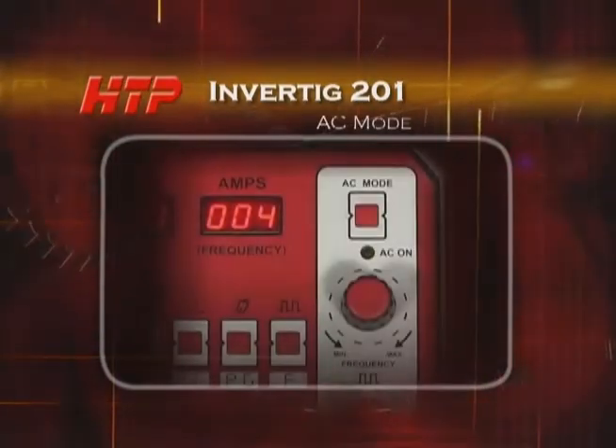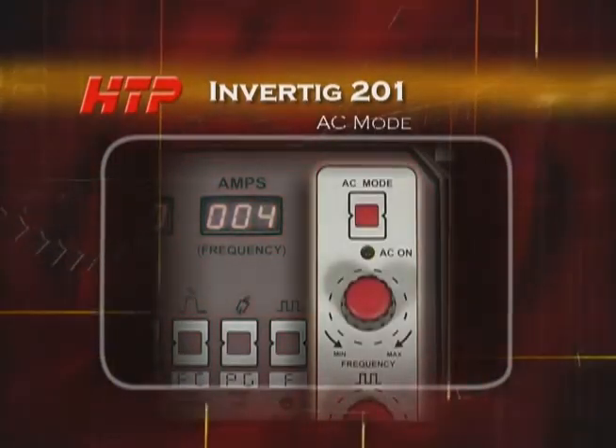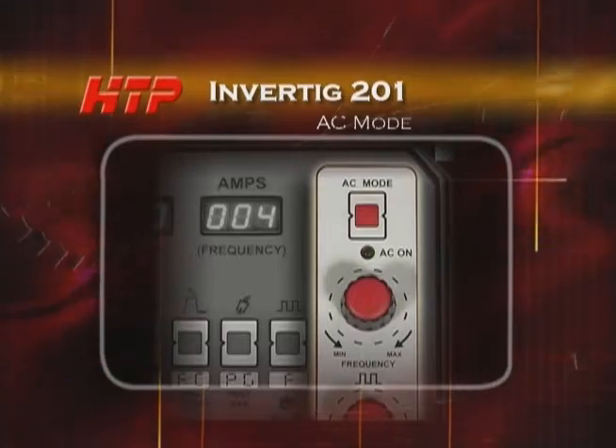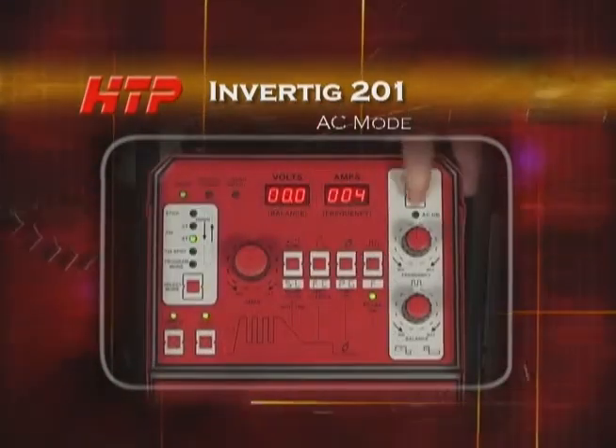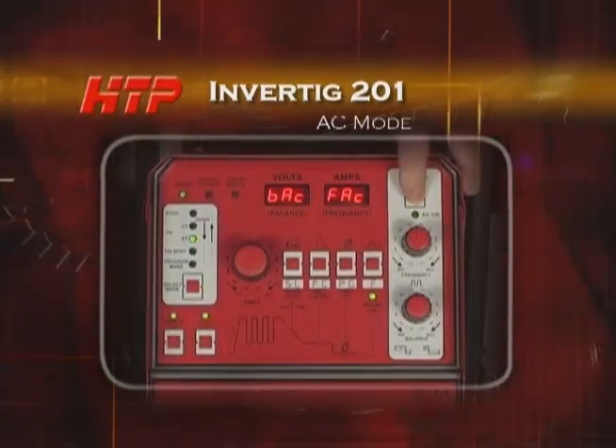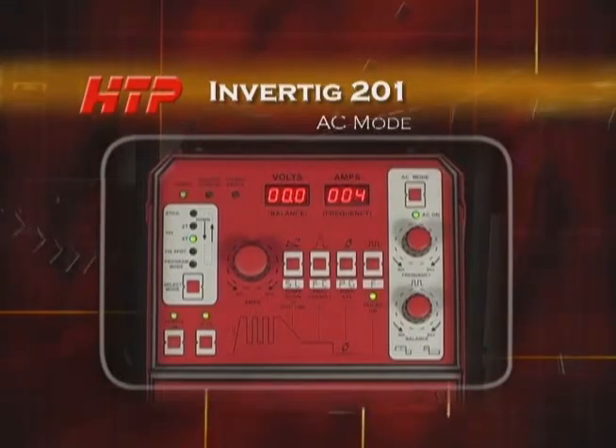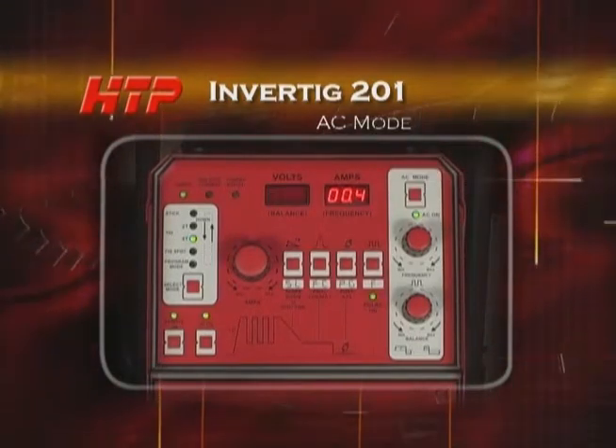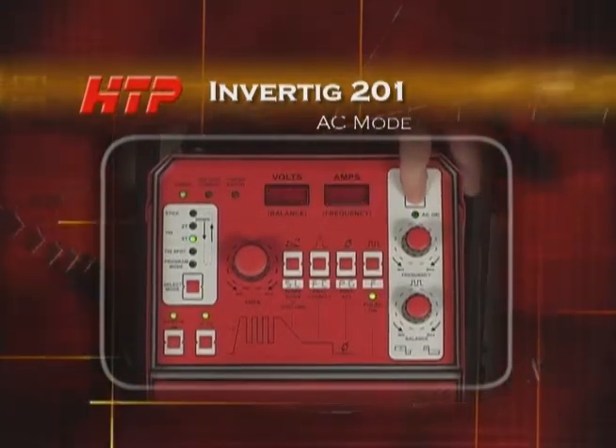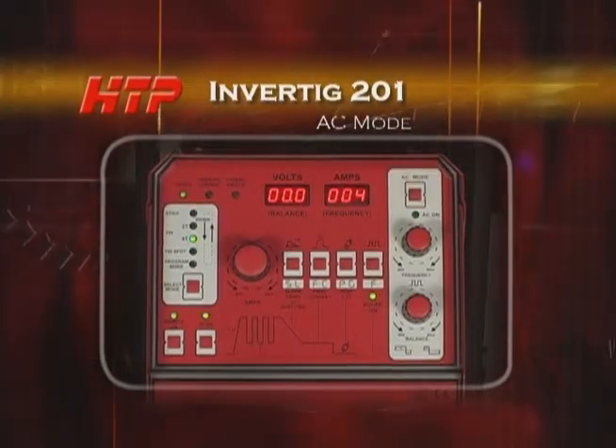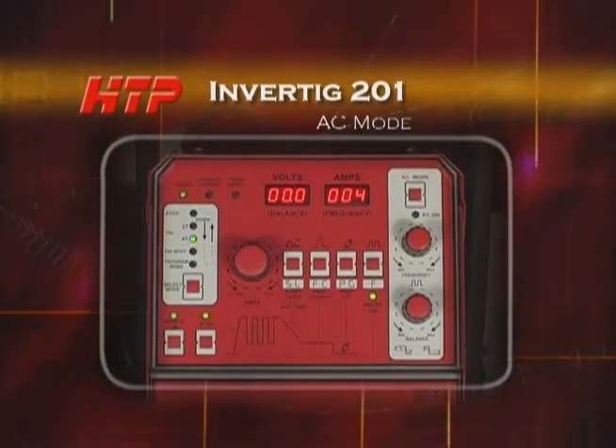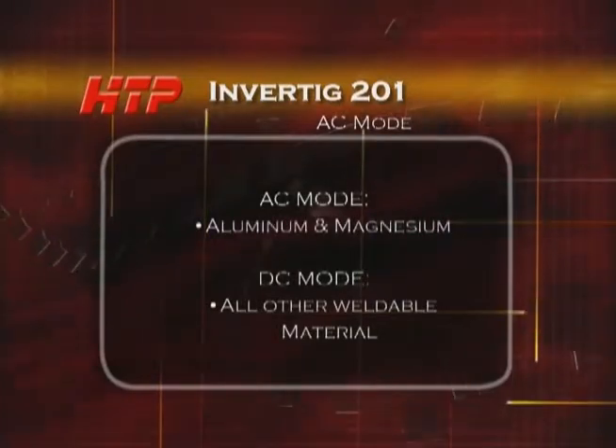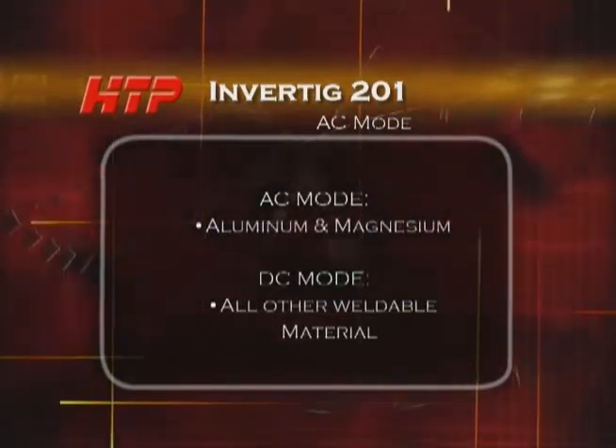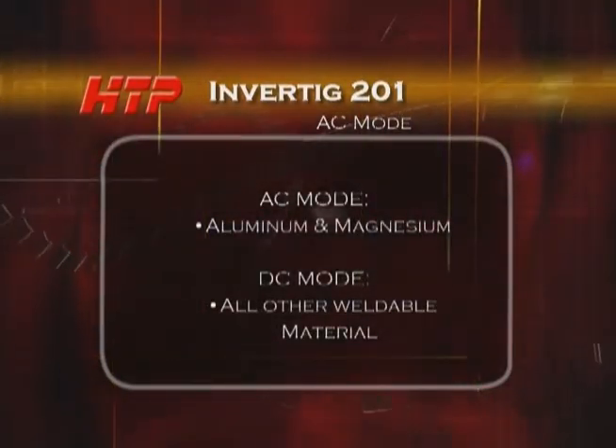The AC welding mode controls whether the 201 is in the AC or DC mode. Depressing the button and releasing it illuminates the green AC light, indicating the machine is in the AC mode. Depressing the button until the green light goes out puts you in the DC mode. Remember, AC for aluminum and magnesium, DC for all other weldable materials.